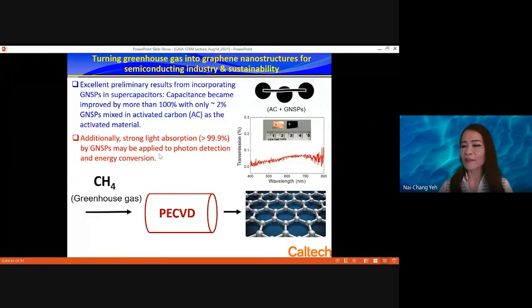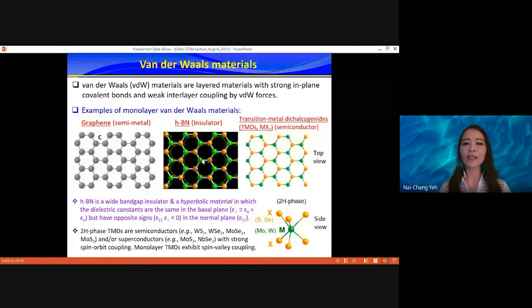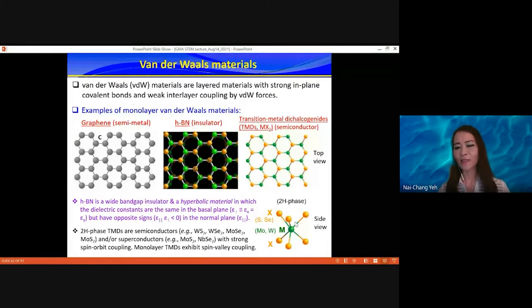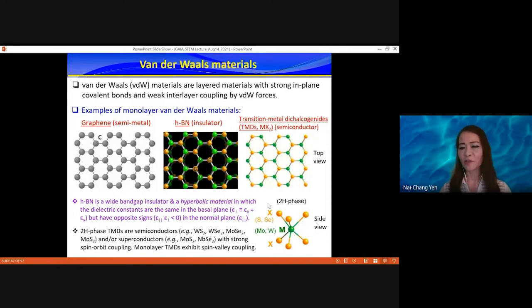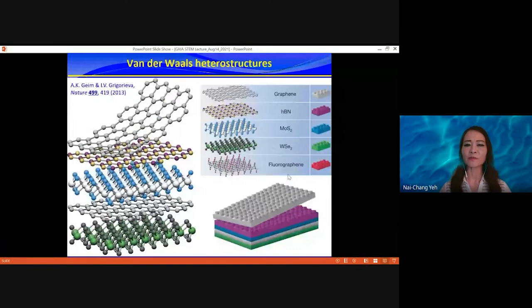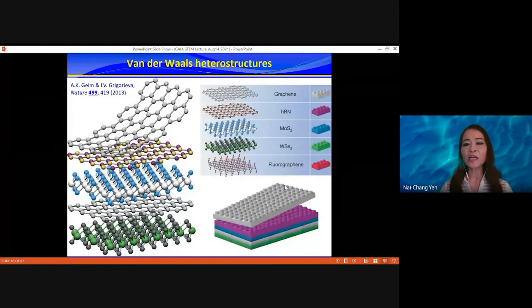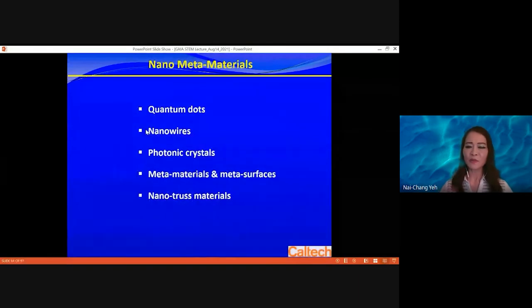There are other nanomaterials called van der Waals materials, similar to graphene. If you change the carbon atoms to boron and nitrogen, you get a one-sheet insulator — graphene itself is a semi-metal. You can also stack triangular lattice patterns of transition metal and chalcogen atoms; viewed from the top they look like a honeycomb structure with three atomic layers per unit cell. These materials are very interesting semiconductors, superconductors, or topological materials. It's almost like playing with Lego — you can stack different materials, even rotate the angle, and create new properties.